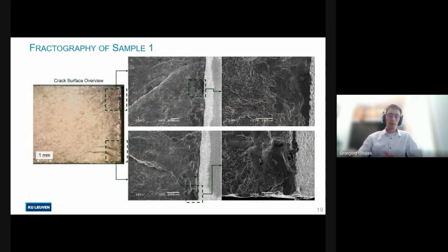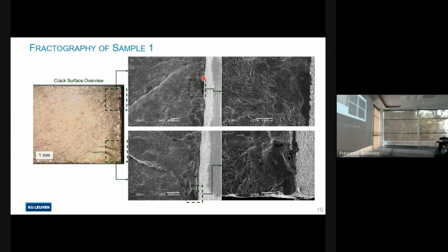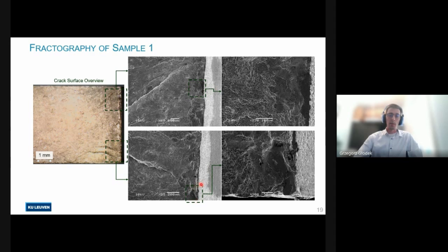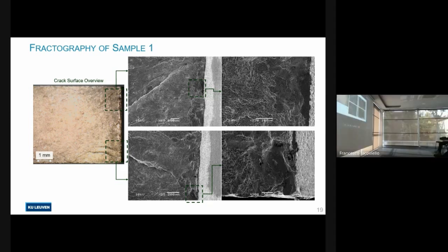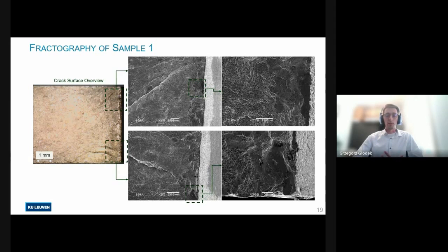If we look at the crack surface, we can distinguish two likely areas where the crack could have initiated. So it's possible that the crack started growing from two regions and later coalesced into one big crack, which caused the failure of the specimen. Also, since we can see the contact area at a relatively high angle under the SEM, we can clearly see the difference between the slip and the stick areas in fretting fatigue.